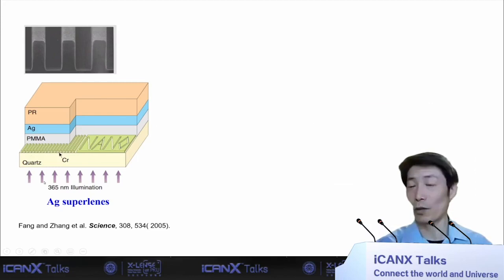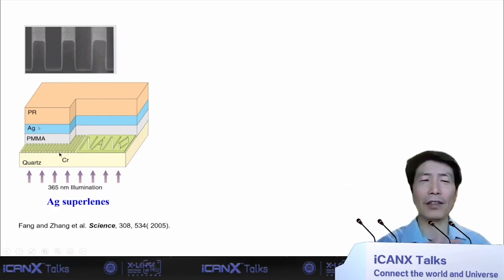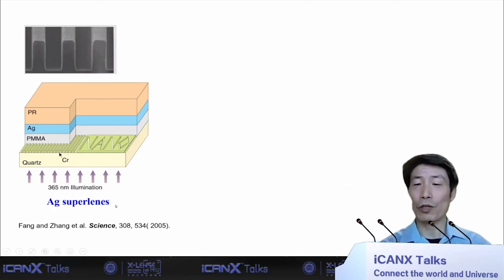light, typical UV light, right? The lens, they're not using a stack of lenses, but instead they just simply use a thin layer of silver. The thin layer of silver acts as a so-called super lens. It can actually resolve very tiny features in the near field. So you can see that now the photoresist is spin cast directly onto the silver film.